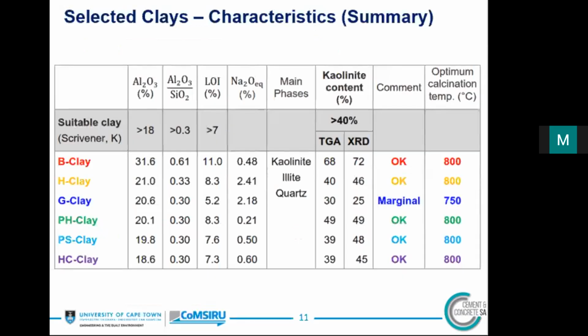Then the second task was to check the suitability of these clays and the optimal calcination temperature. So this involved XRF, XRD, TGA analysis, and also reactivity test. This table shows a summary of XRF, XRD, TGA, and also the calcination temperature. Basically, a suitable clay is one with alumina content greater than 18%, alumina to silica ratio greater than 0.3, and LOI greater than 7%. But what's most important is the kaolinite content, which has to be at least 40%. Based on these results, we decided to select B clay and H clay from South Africa, and PH and HC clay from Tanzania for further work.